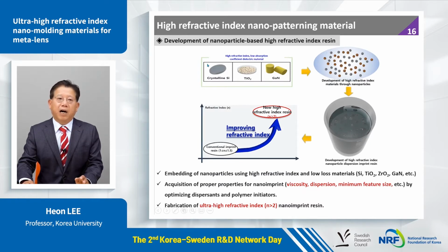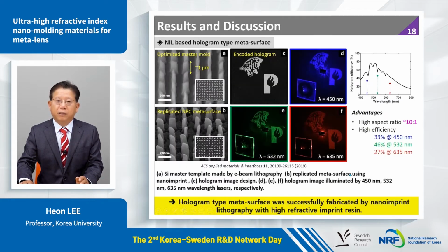And how can we make a high refractive index nanopatterning material? We choose silicon, titanium oxide, or gallium nitride. Those are high refractive index materials. We can turn this bulk material into nanoparticles and disperse those nanoparticles into the liquid phase imprint resin. Then we get two things: one, high refractive index; two, nanopatterning capability. So we can have a refractive index higher than 2.0, and also the capability of being used in nanoimprint lithography.